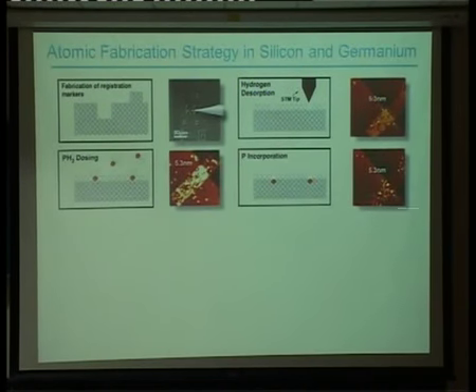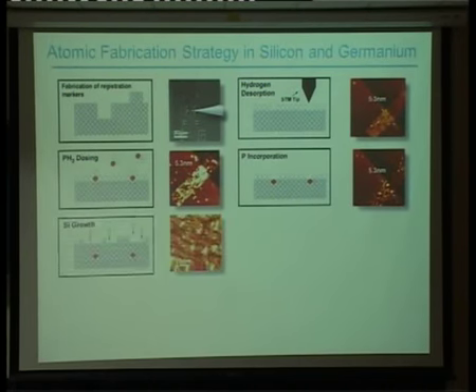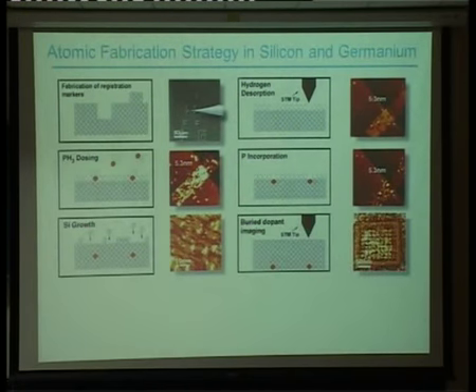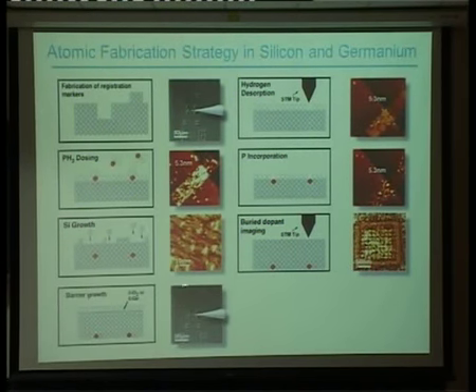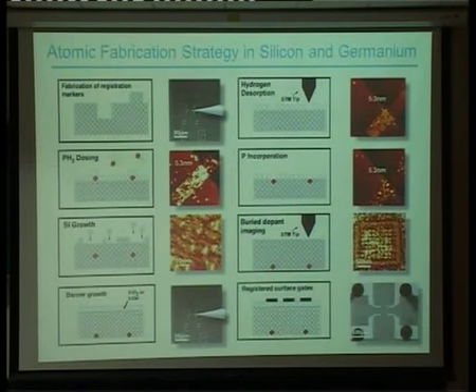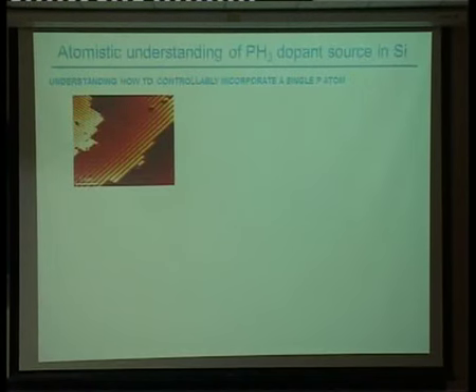You then heat it up, and this is quite a critical stage because this encourages the phosphorus to go into the top layer of the silicon and to kick the silicon atoms out, and thereby they actually stay in place with 3 covalent bonds to the surface. You take it across to the MBE system, you encapsulate with low temperature MBE, so the phosphorus doesn't move. You can actually image that with the STM, you see them below the surface. And then using these registration markers, you take it out of the system, and then you make electrical contact to the buried device below. So the key part of this is there's going to be a few slides of chemistry about how you can make a single atom device.